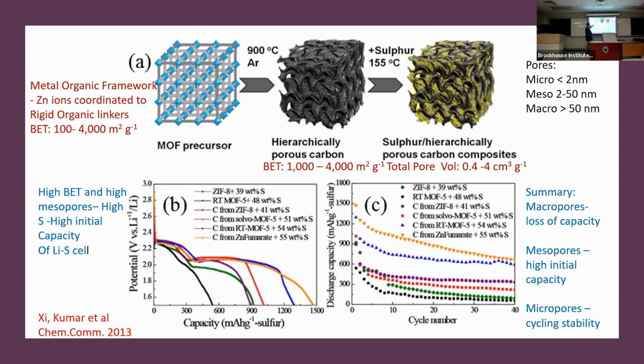We used a metal organic framework material and pyrolyzed it. Because it's got zinc in it, which also vaporizes, we converted it into a hierarchically porous carbon. The beauty of using metal organic frameworks is that there are thousands of them available, and they start with extremely high surface area already. The BET surface area can be 1,000 to 4,000 square meters per gram, like zeolite materials. And we incorporate the sulfur into them.